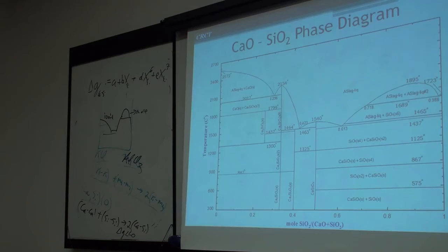Again, the quasi-chemical model is only kind of an approximate thing for the right-hand side. But in many ways, I think it's better than with the aluminum chloride because it really does model. On one side, it models the complex formation. On the other side, the silicate, basically for complex ion formation. And on this side over here, it more or less models the network modifying, where the calcium oxide is clipping the bonds. But the model is the simple one sublattice polynomial model, or quasi-chemical model, with the Z ratio to be 2 to 1.